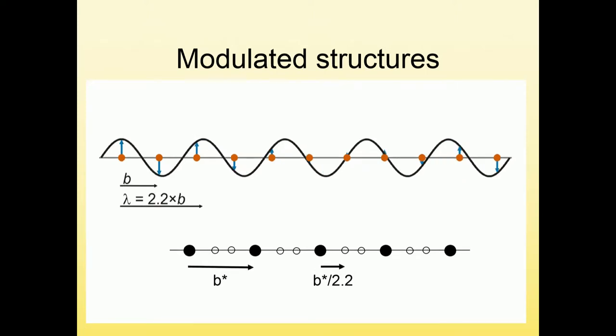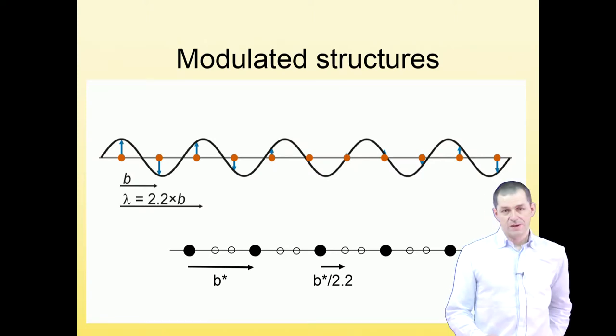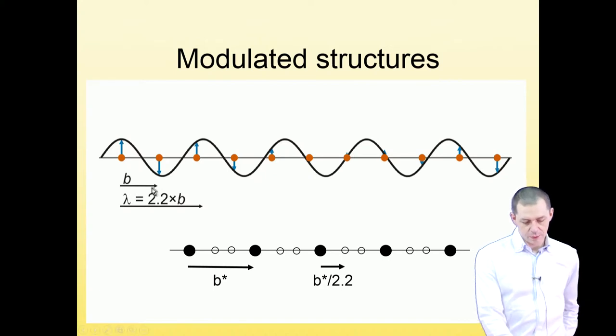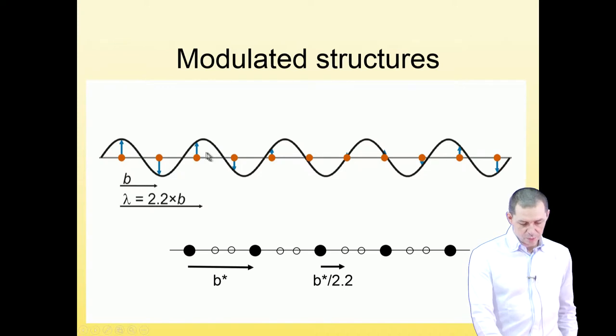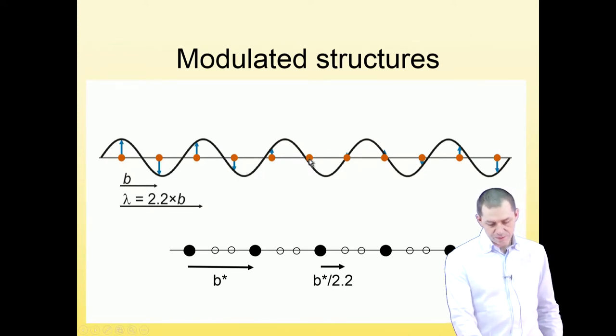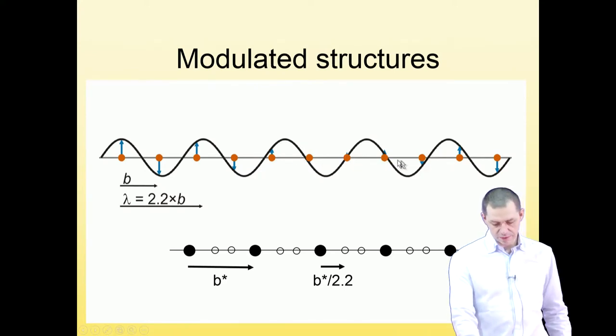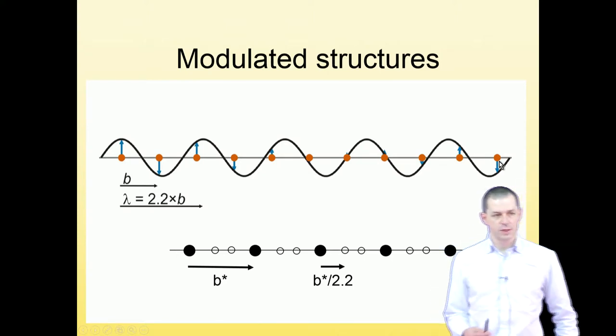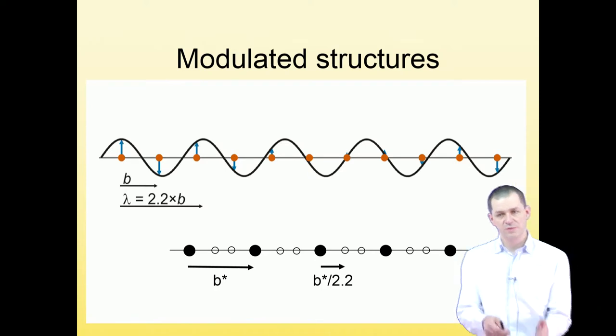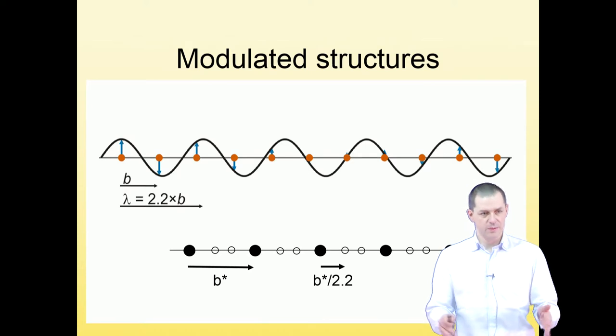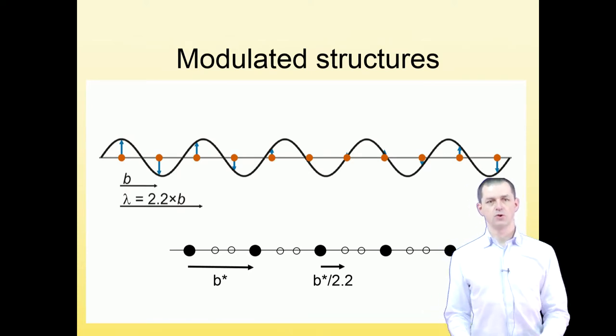Now you can imagine that the wave that tells you how much you should shift the atom does not have a wavelength of 2b, but it has a wavelength that is different, that is not a simple multiple of the average lattice. So in this case, this is a wave that has a periodicity of 2.2 times b. If you do that, you obtain again a structure which is not periodic with the periodicity of b. The atoms are shifted, see, up, down, but the amplitude changes because the wave shifts. Here the amplitude of the shift is essentially zero, and here it's again up, down. What we get now is a structure which is not that much different from the previous structure. We obtained it with the same idea. We just slightly changed one parameter, the wavelength of the wave, but we get a structure which is almost non-periodic.